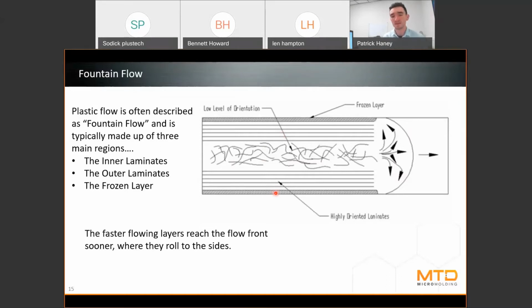The frozen layer is actually a stationary layer that just kind of lays down and stays there. And the reason why that happens is because the steel that makes up the flow channel, the steel of the mold, is very cold relative to the temperature of our molten plastics. So as the outside layer of the polymer comes in contact with that tool steel, the tool steel will suck all the heat out of it right away. And it will actually freeze and solidify, right? So that will become important in a couple concepts that we talk about near the end here.